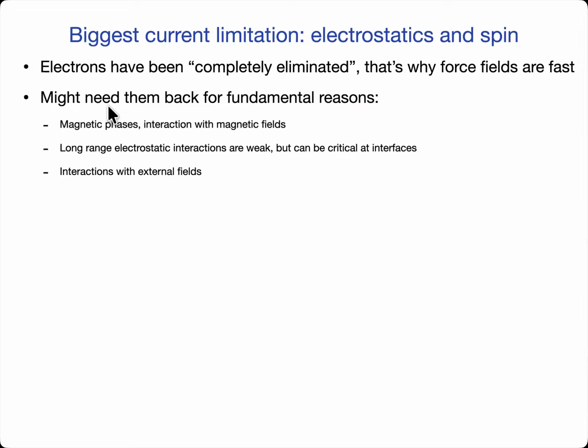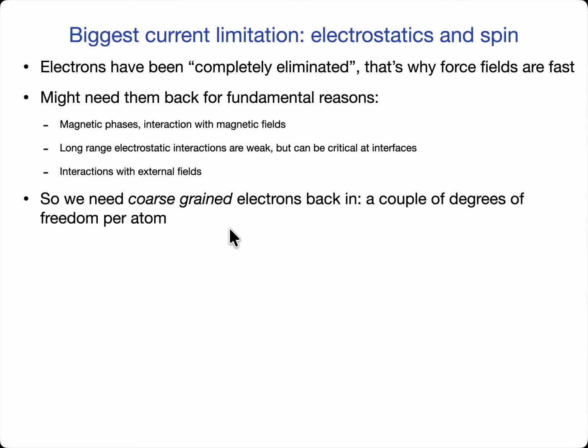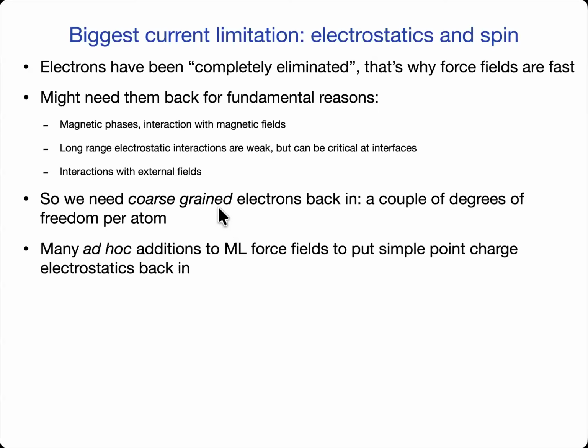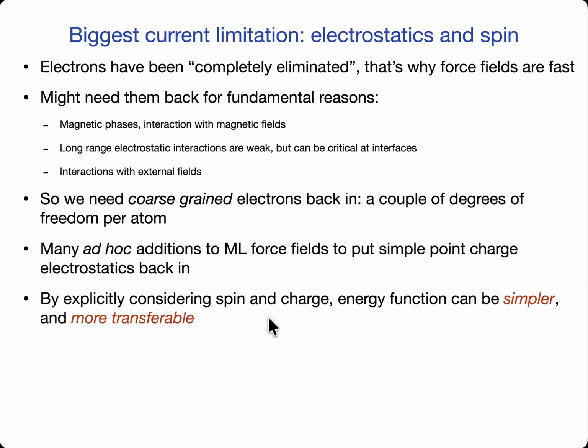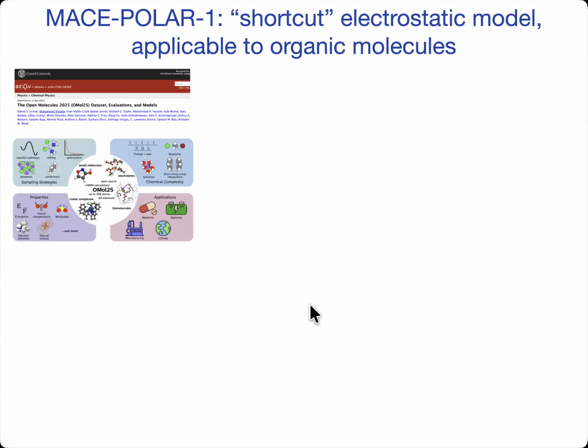And I think people broadly agree that we sort of need them back a little bit if you want to do magnetism, if you want to do long-range electrostatic interactions, which are weak but important, for example, in the crystal structure prediction problem, or at interfaces, then we need this coarse-grained description of electrons back. And this is, of course, not a new idea, right? So many people have done this in some ad hoc way. And what we hope to do by explicitly considering charge and spin and doing self-consistent electrostatics is that even the energy, not just the electric response, will be better, but models will be simpler and more transferable.